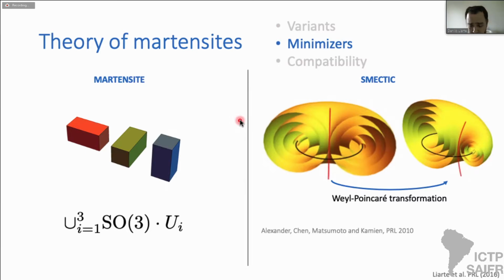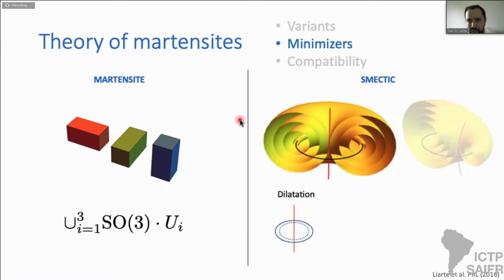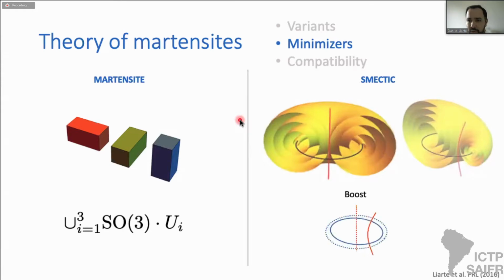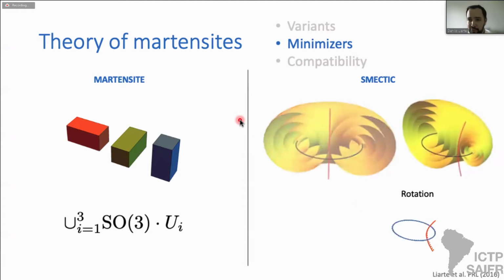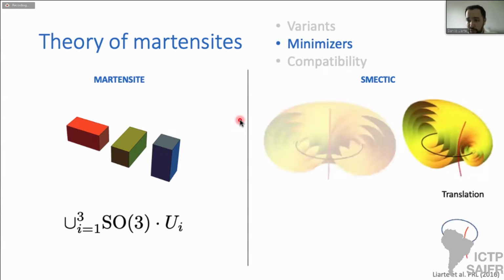eccentricity, orientation, and position. Now, just as a reminder, this Weyl-Poincaré group has all the transformations of the Poincaré group plus dilatations. So you can start by applying a dilatation in your system, which will generally change the size of the singular unit circle. Then you follow this with a Lorentz boost, and depending on the parameter of your transformation, the velocity between quotes, you can control the eccentricity of the ellipses and the hyperbola of this focal conic domain. Now, the next two steps are trivial. You apply a rigid rotation that will determine the orientation, and then a 3+1 dimensional translation, which will place the focal conics where we want them to be.